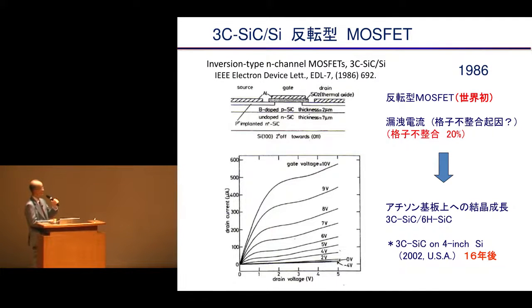And then we went on to develop the MOSFET. This is using the silicon substrate and N-type silicon carbide, and on top of that, P-type silicon carbide, and the PN junction is here. But the issue is the silicon and silicon carbide. Between the two, there's about 20% lattice mismatch of the atoms. So this means that one side will be pulled, and this mismatch was seen between the P and the N.